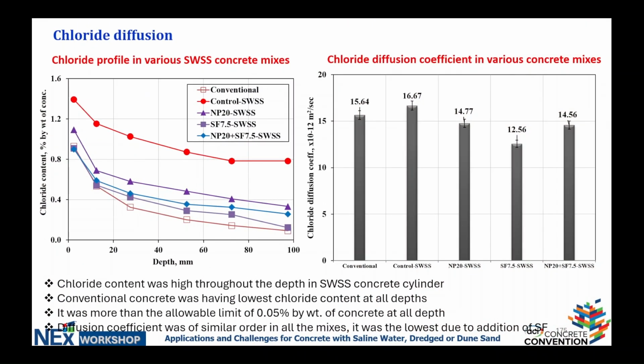The chloride diffusion, I think Osama spoke to that issue very effectively. Why is this important to us if we don't really have steel in it? It's a very good indication, even though it was developed for steel, of the quality and the durability of the concrete itself. And here you can see for yourself what the differences are between the two. It's interesting to see the chloride profile. There is a very significant variation between the benchmark and the other four mixtures, but in terms of the chloride diffusion coefficient, basically they are all the same.